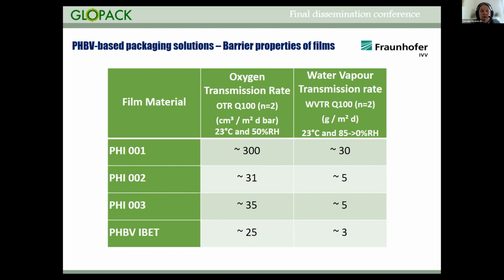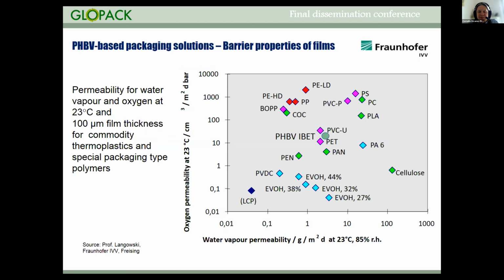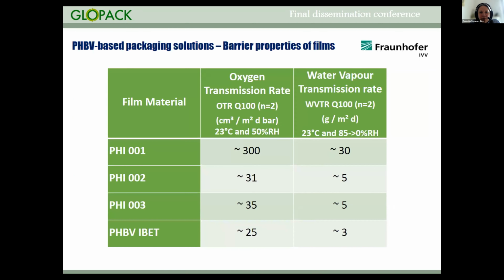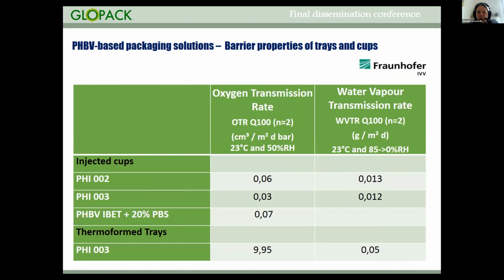You can see that the pure PHBV samples showed good barrier properties. The permeability for oxygen was below 40 cubic centimeters, and the water vapor permeability is under 6 grams. These values are low in comparison to other biopolymers. Sorry, one back. The reason for the higher values of PHI 001 is that it is a blend with another biopolymer. Therefore, we have higher values here. You also see that the project material in the last line showed slightly better barrier properties compared to the commercial grade.